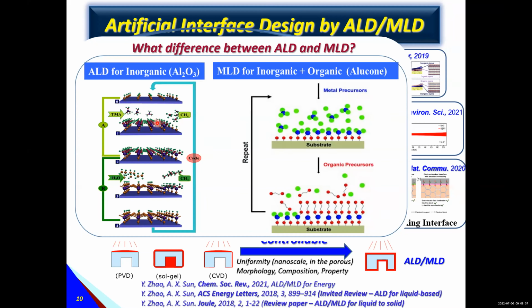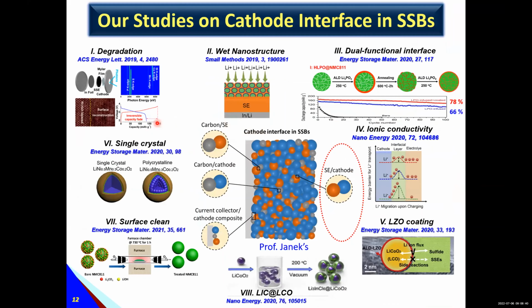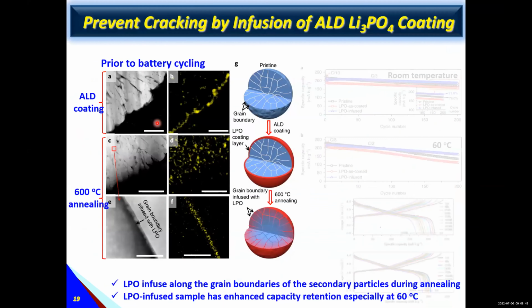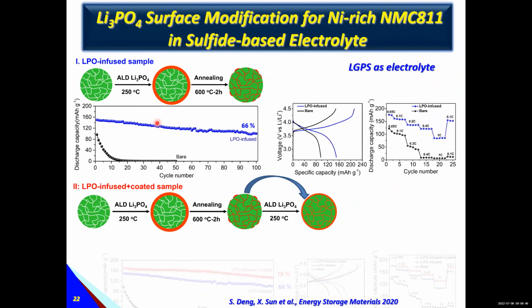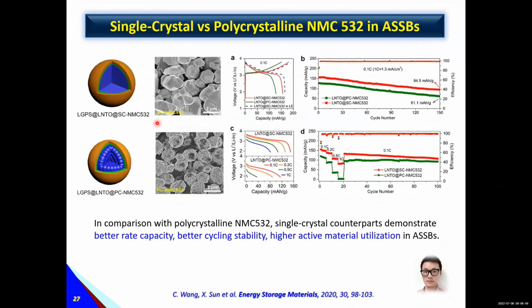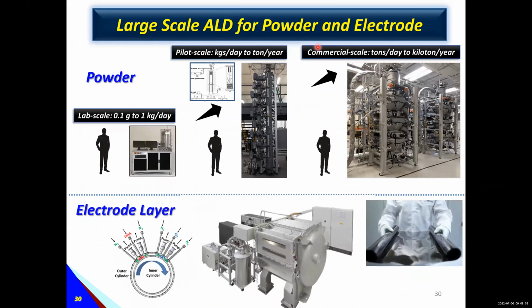Even for powder, as I mentioned, mass production is now available at 20 tons per day, and it is also available for uniform deposition. The reason is that they combine the chemical reaction process with a fluidized bed. During the ALD coating, they have fluidized powder, allowing the powder to flow. That's why they can produce a big amount. So in general, yes, ALD can deposit very uniformly everywhere.